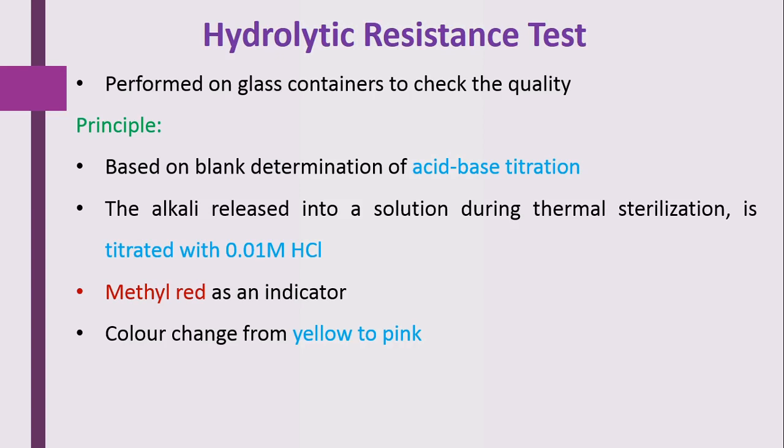Here the test is performed on the glass containers. The distilled water is stored in it, and they keep it in the autoclave for thermal sterilization at 121 degree centigrade for 2 hours. After completion of that time, the liquid which is filled in it is removed, and that particular liquid is called the test sample.